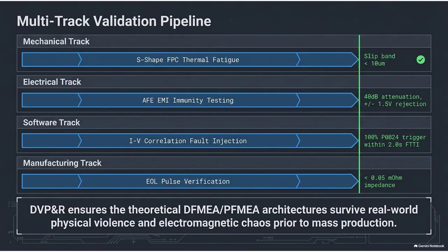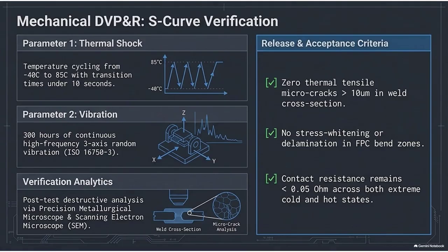The engineering standard dictates that there cannot be any fatigue slip bands, which are the microscopic stress lines that eventually become cracks, and absolutely no physical cracks larger than 10 micrometers. 10 micrometers. To give everyone a sense of scale, a standard human hair is about 70 micrometers thick, so they are hunting for stress cracks that are 1/7 the width of a hair after 300 hours of torture. Exactly. And electrically, the resistance across that tortured joint must still remain strictly under the 0.05 Ohm limit. If the wire cracks or the resistance drifts, the design fails DVP&R and must be entirely re-engineered.